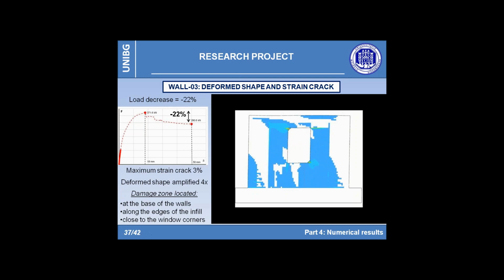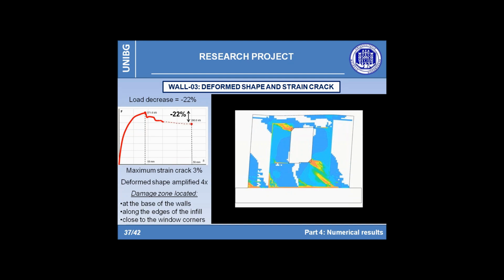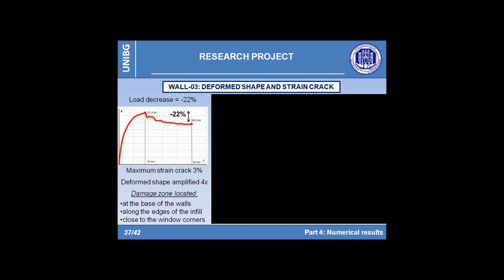Coherently with what was done for the previous test, the evolution of the damage zone in terms of crack strain is reported, being in red the areas affected by strain higher than 3%. The deformation shape also in this case is amplified 4 times. The crack evolution reveals that from 0.65% drift, the infill panel is entirely damaged, and that the layout of the cracks appears stable and uniquely defined.